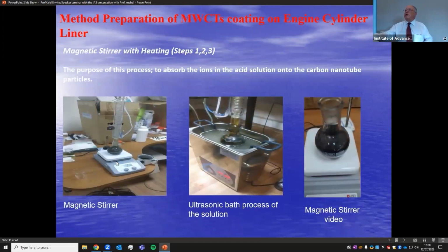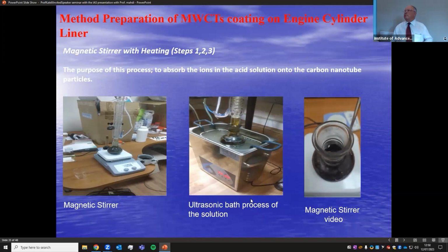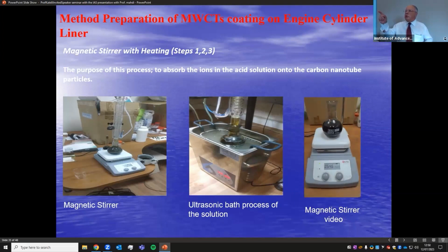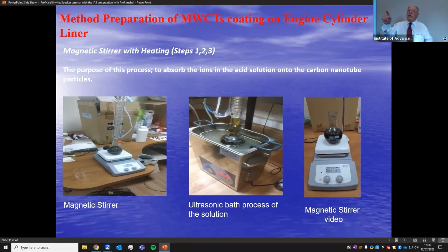So you see, this is a magnetic stirrer, and after the ultrasonic bath process, we use the magnetic stirrer. This is the first solution with sulfuric acid, nitric acid, and multi-walled carbon nanotubes. So you obtain this heavy solution.